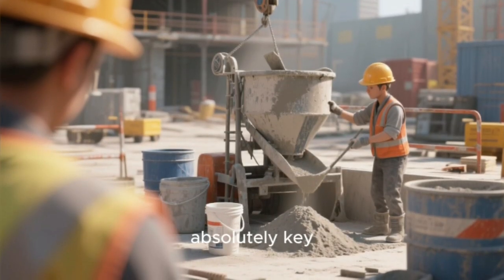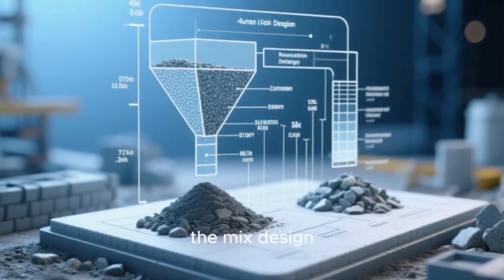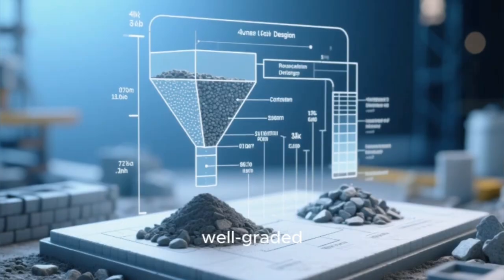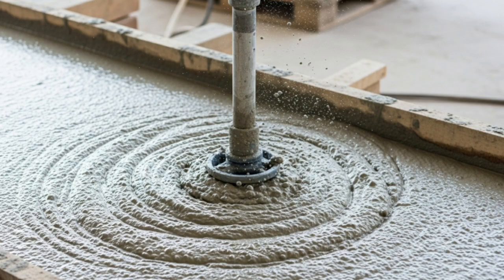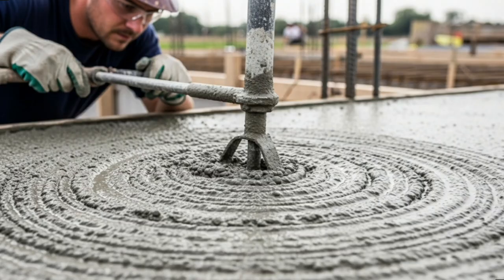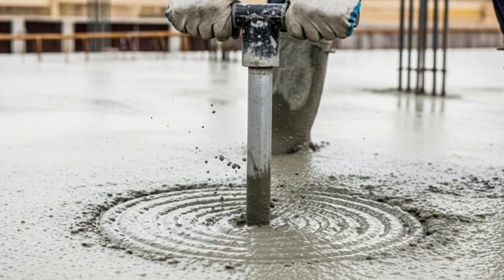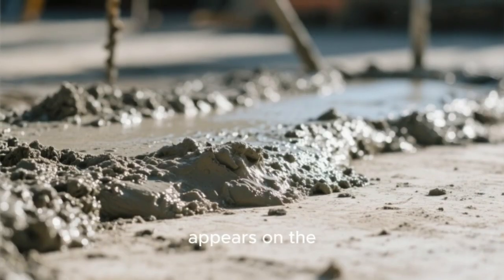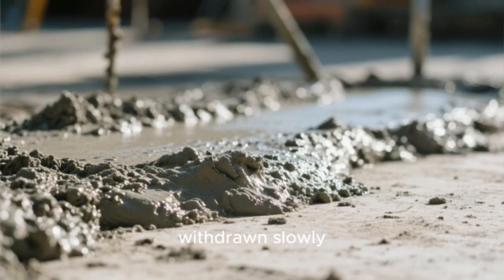Prevention is absolutely key. It begins during the mix design phase by ensuring the concrete has adequate workability and a well-graded aggregate for the specific placement conditions. On site, the golden rule is proper vibration. The vibrator should be inserted rapidly into the concrete, held for typically 5 to 15 seconds until the air bubbles stop rising and a glistening film of paste appears on the surface, and then withdrawn slowly.